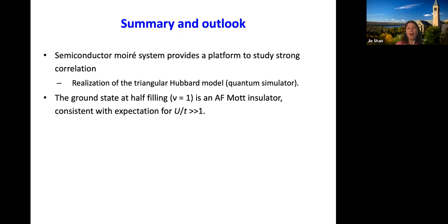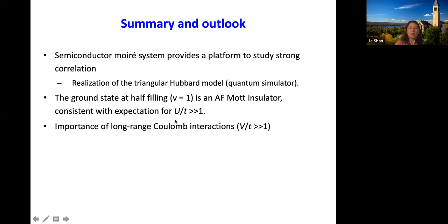The ground state at half filling is an antiferromagnetic Mott insulator, and this is consistent with expectation in the limit of large U over T. The long-range Coulomb interaction is also important in this system, and that tells us V is also bigger than t, and for some states maybe comparable. So if you can tune those parameters, lots of interesting things are expected.